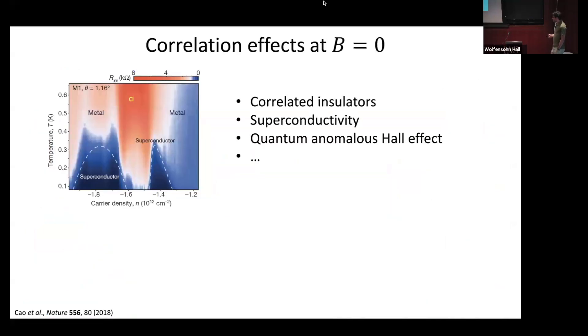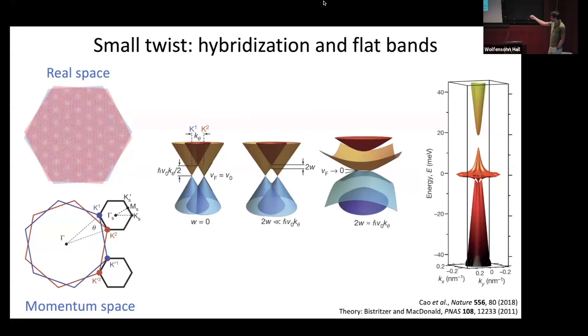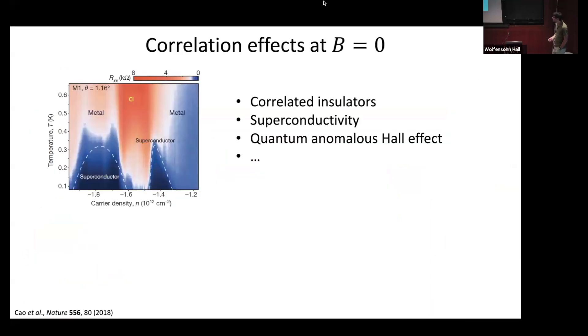You get eight flat electronic bands separated by energy gaps from more dispersive bands. This factor of eight comes from two Dirac cones with spin and valley degrees of freedom. When you have flat bands, correlation effects often dominate over kinetic energy. From the very first observation of magic-angle graphene — where the magic angle of ~1.1 degrees is set by this competition between hybridization and momentum separation — the first observation was superconductivity and correlated insulating behavior when you partially fill these flat bands.